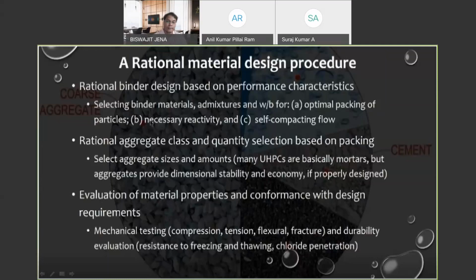So if you look at particle size distribution of cement, you will have sizes from 1 micron roughly to about 100 microns. So normally from 1 micron to 100 micron, generally it is distributed. So what happens to the sizes smaller than 1? We don't bother about sizes more than 100 micron because we have sand which will fill in those spaces. But what about smaller than 1?